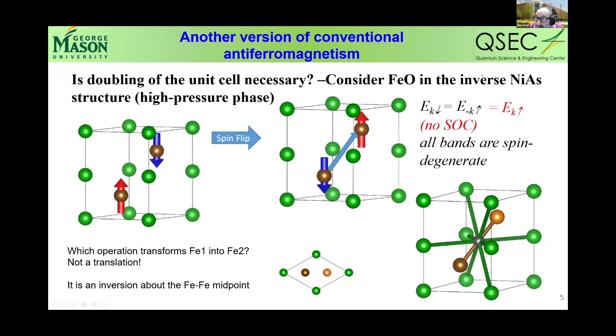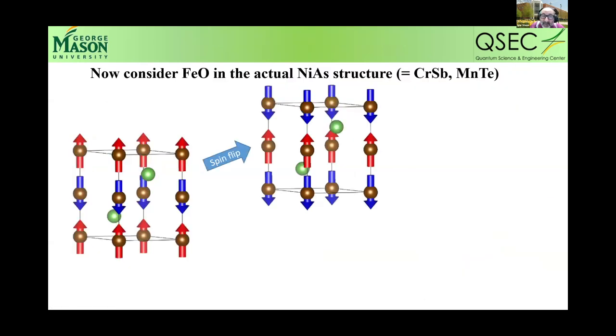Now, if the same symmetry operation, inversion in this case, is also equivalent to spin flip, time reversal, that means that these two equalities hold independently. That means that basically for a given momentum k, spin up and spin down states are degenerate. So we are back in the realm of conventional antiferromagnetism.